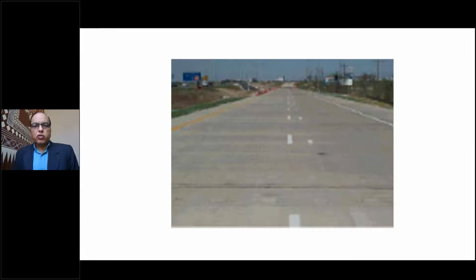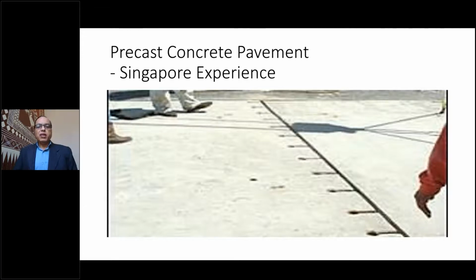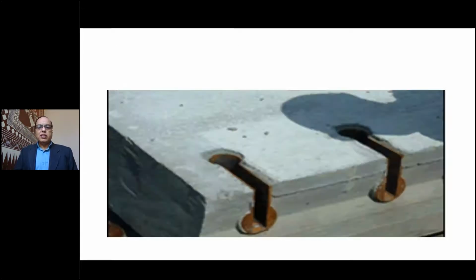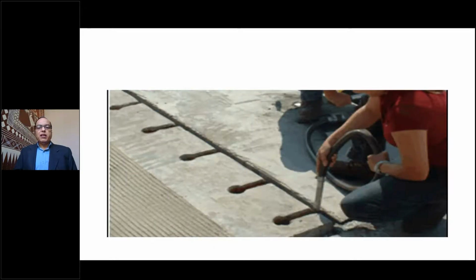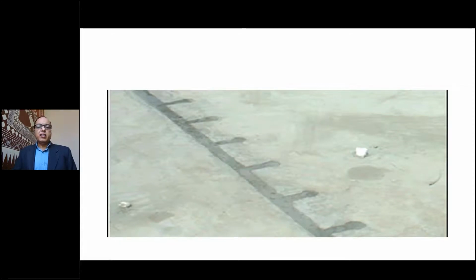Therefore, unlike cast in situ pavements, these precast pavements can be constructed very fast because the panels are made beforehand and only laid at site. In fact, in other countries, they have been making these precast roads. In the US, they adopt a particular technology. In Singapore, they adopt a different but very similar technology. It was our dream that we should try this technology, but finally it has been implemented on a small road project, which is still ongoing, and about 400 meters is already constructed. Yeah, this is the Singapore experience, precast concrete pavement. The two precast panels are brought close to each other and they are joined using couplers. You can see that these couplers are grouted, and when they are grouted, this forms a neat joint, and there is no problem at all.